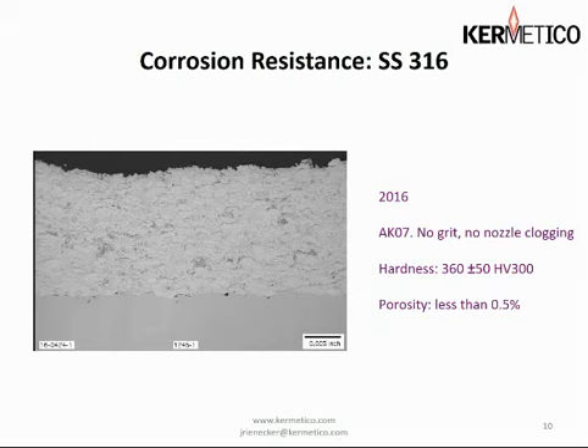Here's a coating of 316 stainless. This was sprayed without aluminum oxide grit, and we'll get into that in a minute. It had no nozzle clogging, had a Vickers 360 hardness, very respectable for that alloy, and the porosity was less than 0.5%.